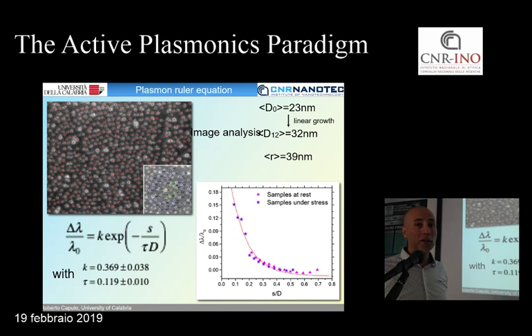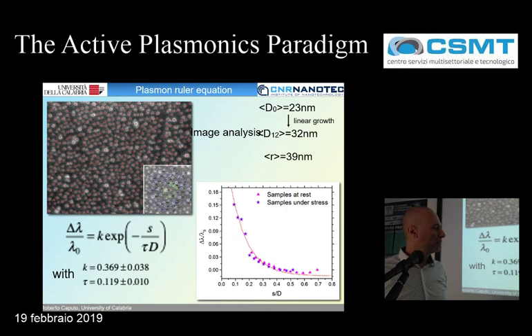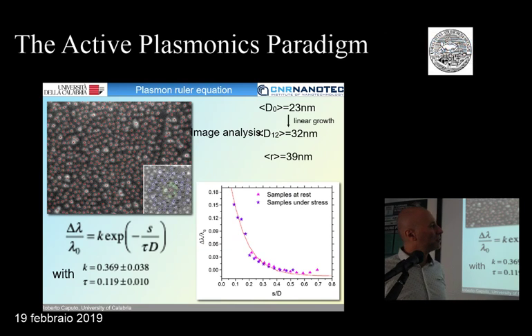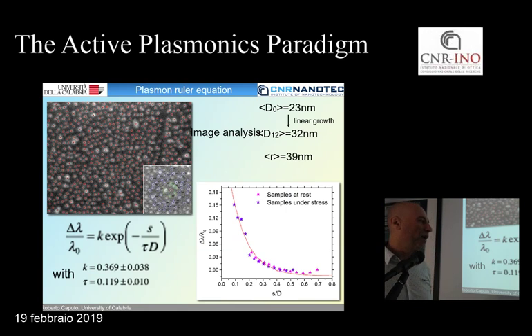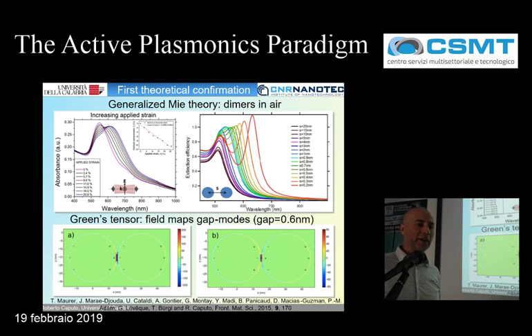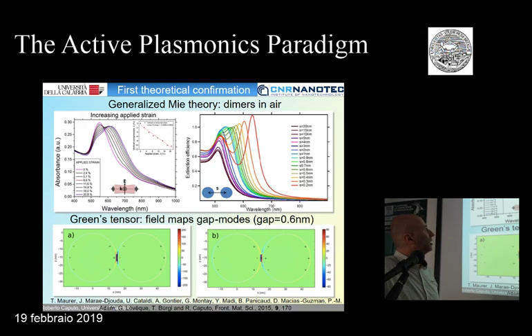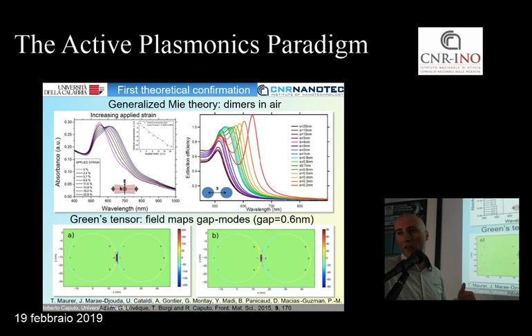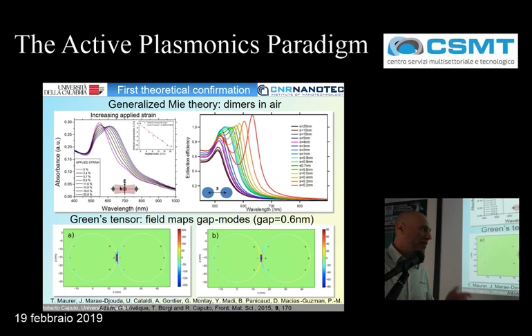follows this line until a certain point, but when you repeat the same experiment and you calculate the ratio between the gap and the size of the particle, in principle you can get this very high change of resonance, this very nice shift that is following quite well what is expected at least. And we tried to numerically explain this behavior, and indeed by just considering the coupling you can find curves, theoretical behaviors which are very similar to the experimental one. Of course in this case the gaps we are considering are very small, but the simulation was not considering the presence of the substrate, so in practice there is some discrepancy, but the general qualitative behavior is quite impressive.